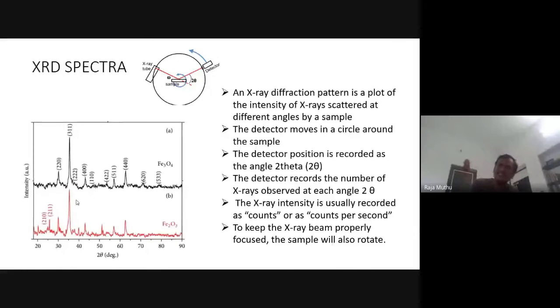The X-ray intensity is usually recorded as counts or as counts per second. To keep the X-ray beam properly focused, the sample will also rotate. I already told you that the sample will rotate at theta speed, whereas the detector will rotate at 2 theta speed. See, this is what we tested, Fe2O3 and Fe3O4.